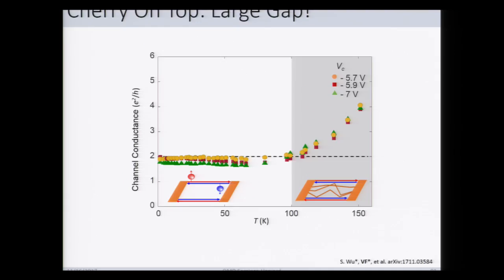And one other bonus, a cherry on top, is that we believe that we've seen a nice signature of the large band gap in the interior. Here's the channel conductance again at close to 2e²/h as a function of temperature. And we find that it is roughly constant up to about 100 Kelvin and then starts to go up. In this region, we believe that the 2D carriers here have been thermally activated and are starting to contribute to the channel conductance. But everywhere below 100 Kelvin, it appears that the system is dominated by the edge modes, which holds promise for topological devices that work at above 4 Kelvin.